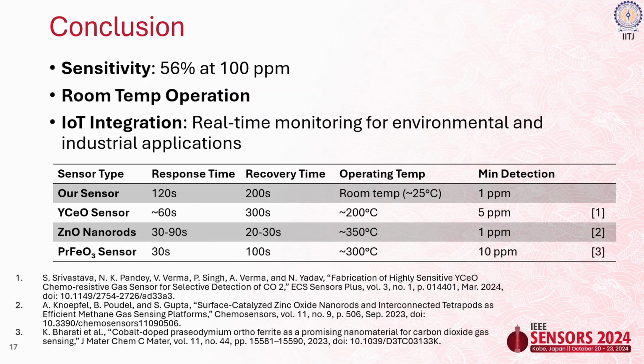So in conclusion, we made a sensor which has a sensitivity of 56% at 100 ppm. The greatest advantage we are getting is room temperature operation. And we are able to even do an IoT integration of it. Compared with some of the sensors that have been reported earlier, we have a bit higher response time and a bit higher recovery time, but the operating temperature is drastically reduced from 200, 250, 300 degrees to room temperature.